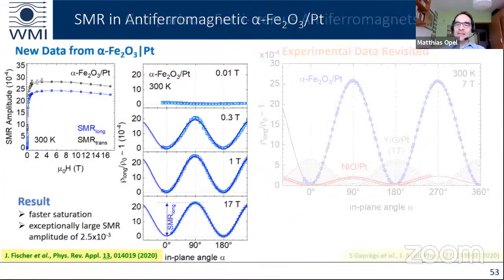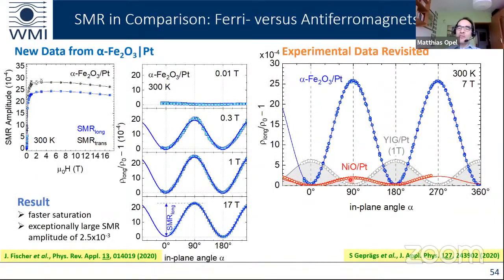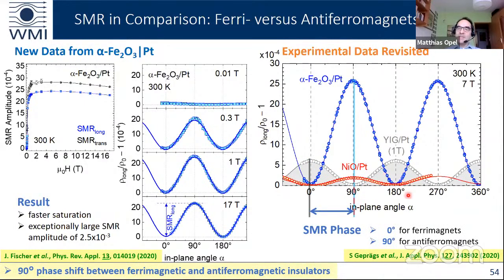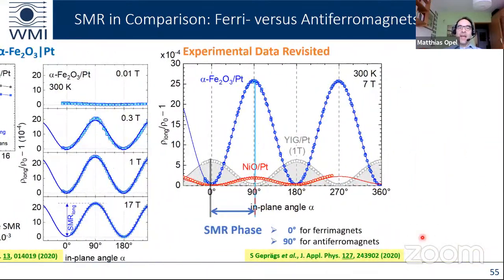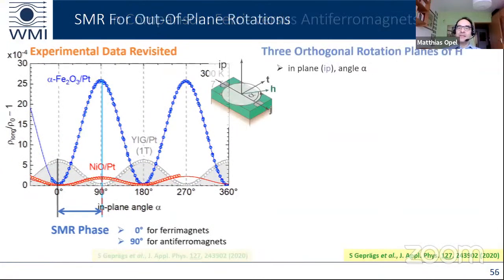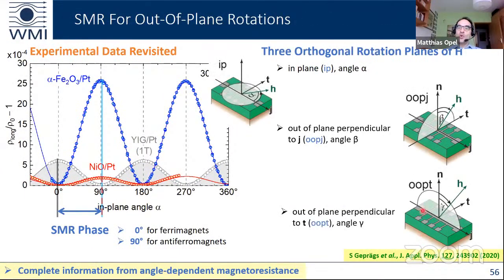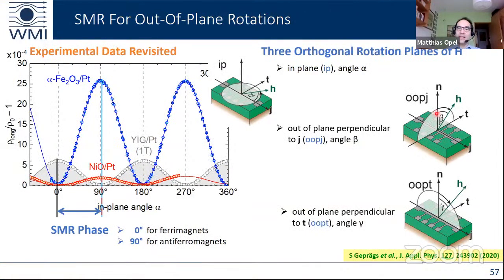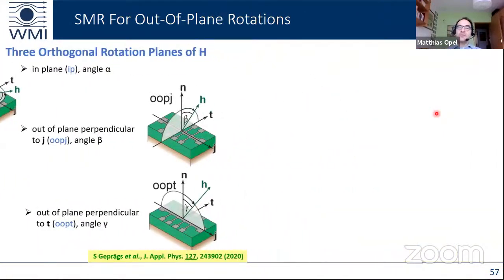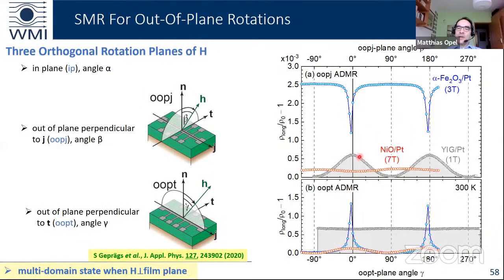So I will come to the end, and I want to compare here the ferromagnetic insulator YIG with platinum and the antiferromagnetic insulators hematite and nickel oxide with platinum. You clearly see the shift by 90 degrees. So it was 0 degrees for ferrimagnets and 90 degrees for antiferromagnets. And I can show you at the end the other two rotation planes when we rotate the magnetic field there. Then you see again in gray the well-known result from platinum and YIG.